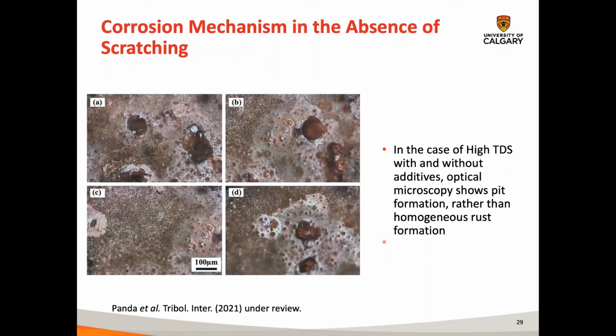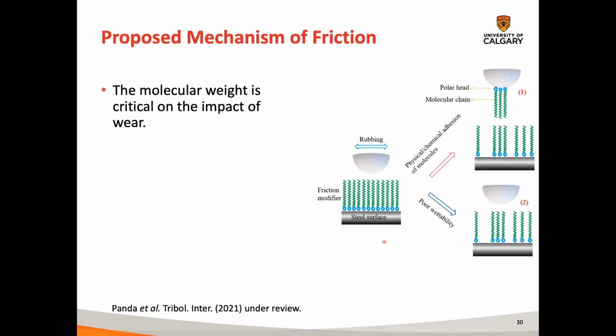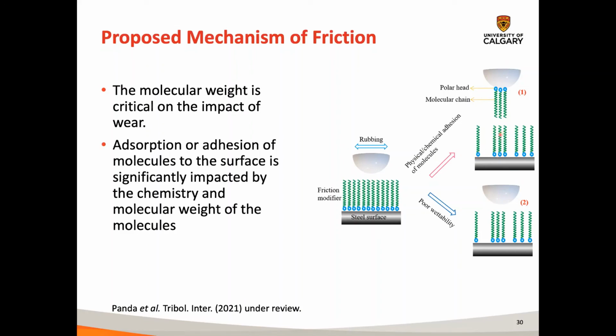We looked at the corrosion mechanism in the high TDS water away from the worn areas, and we saw that pitting formation was the likely mechanism of corrosion in these cases. And so basically, I'm skipping over a bunch of things that we looked at, but what we think is happening is we add these organic friction modifiers, and they sort of form these groups on the surface. They adsorb on the surface, and with the higher molecular weight, we see adsorption on both the counter surface and the substrate, which really reduces our friction coefficient and wear rates.